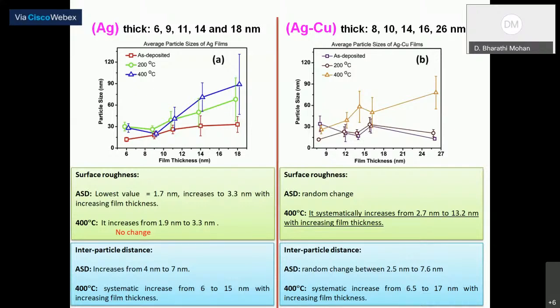But if you look at the case of silver copper bimetal thin films, it is very much confusing at a very lower thickness, in case of as-deposited and 200 degree annealed films. But when you anneal the film at 400 degrees Celsius, there is a systematic increase in the particle size, which goes from 30 nanometer to 85 nanometer.